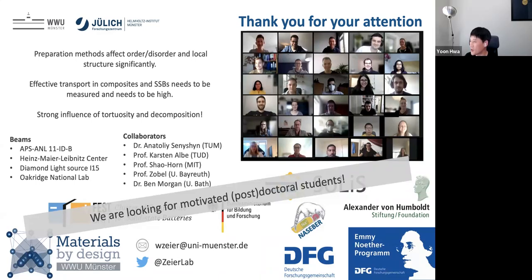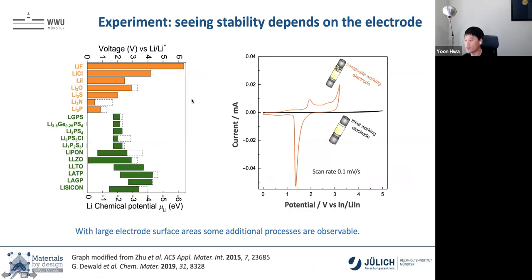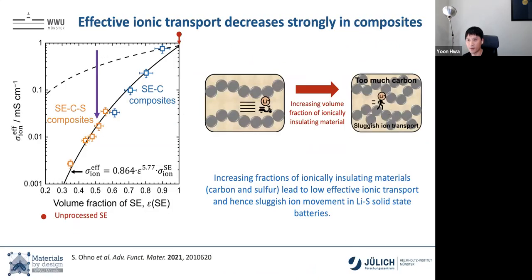Thank you. So I'm interested in your solid state lithium sulfur battery work because I'm working on lithium sulfur batteries. Especially the plot that you showed, the ionic conductivity as a function of volume of solid electrolyte in the composite electrode was very interesting. So did you consider the contact resistance of the solid electrolyte particles when you did this? Because sulfur's melting temperature is so low, you cannot sinter the solid electrolyte particles in the composite electrode. So you might have pretty much contact resistance in between the solid electrolyte particles, but I wonder how effective that term would be in the electrochemical behavior.